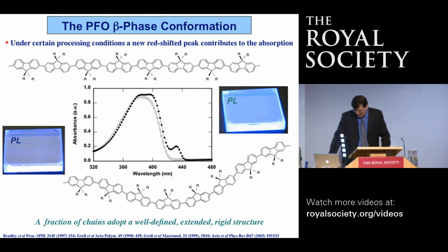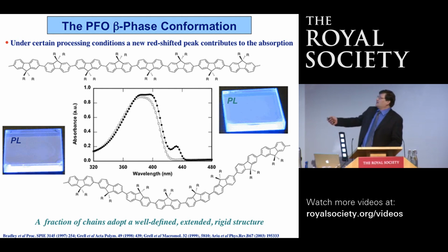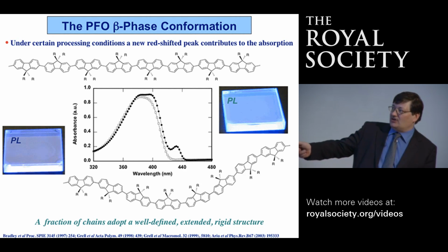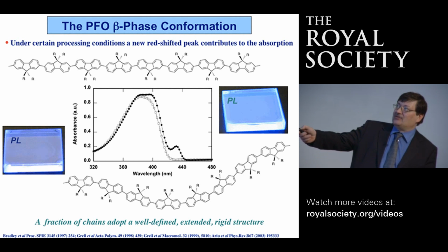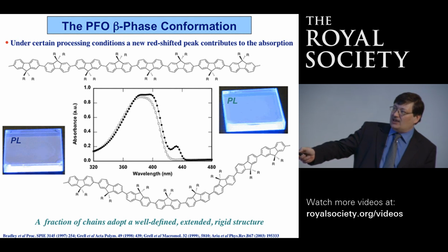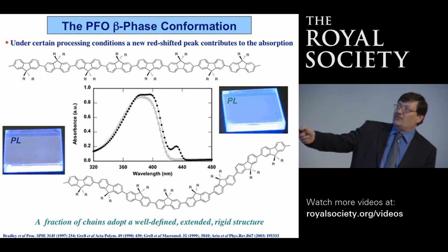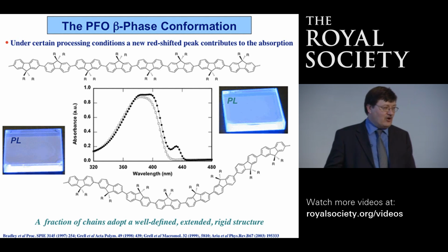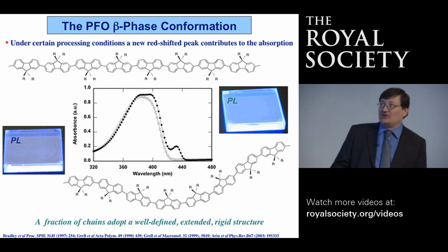And in particular, we're looking at using this beta phase of dioctyl fluorene. So this is an extended chain structure. This is the beta phase structure. This is sort of the more typical, if you like, exploring three-dimensional space structure for the polymer chain. If we arrange that we have this elongated segment, then what we see optically, so this is absorption, is the appearance of a new absorption feature. And this absorption corresponds to having a fraction of segments of polymer chain in this conformation. And it's that same conformation which gave rise to the gelation that we talked about earlier on.